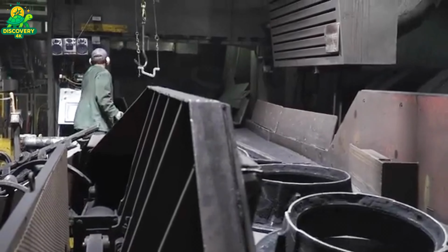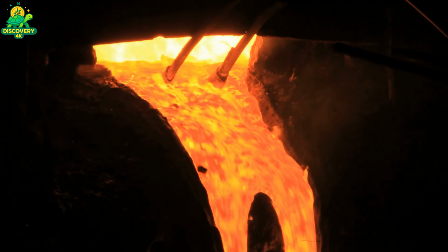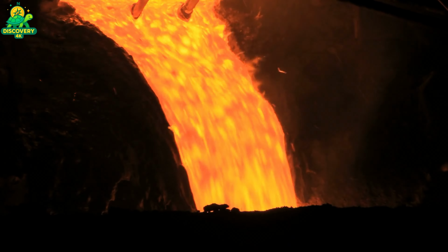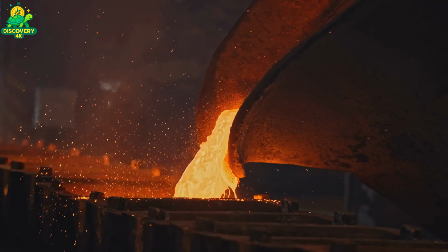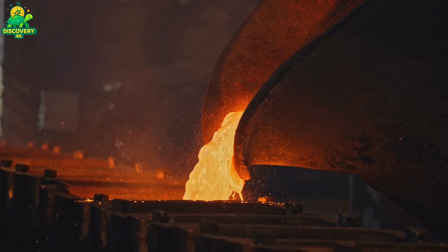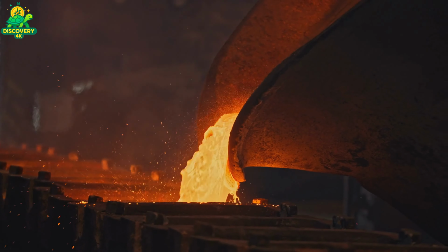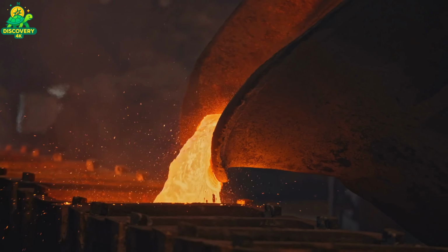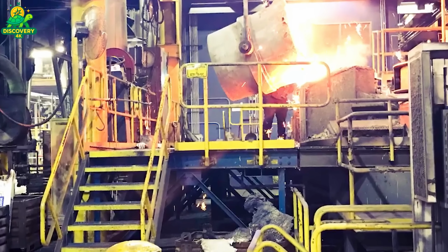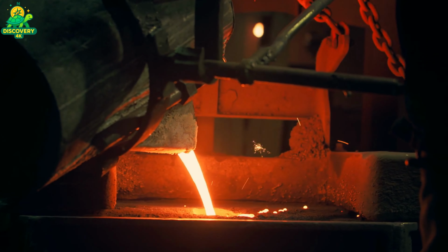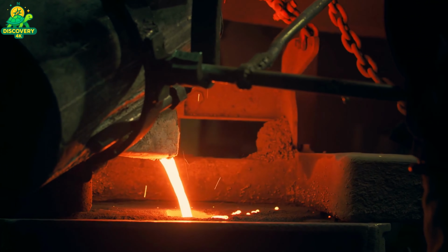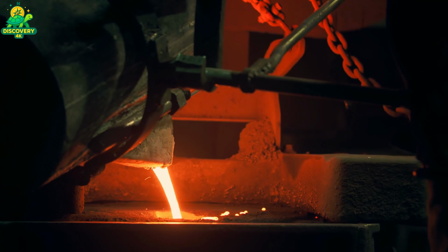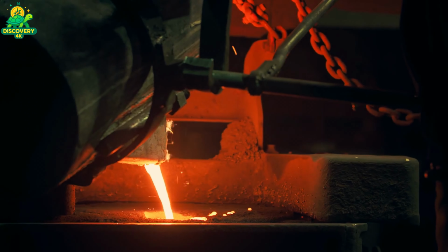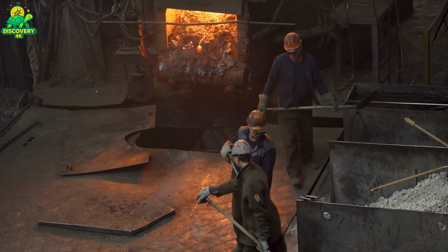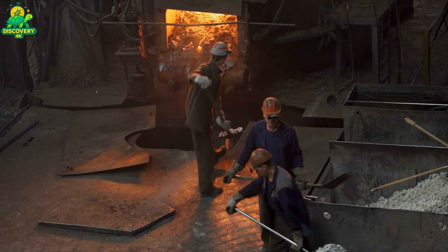The furnace hall is the beating heart of the manhole cover factory. Here, massive induction and cupola furnaces generate temperatures exceeding 1500 degrees Celsius, hot enough to turn solid iron into glowing liquid metal. The process begins when carefully measured batches of scrap are fed into the furnace, layer by layer. As the furnace roars, operators monitor gauges and screens, adjusting oxygen and fuel flow to maintain the perfect melting conditions.